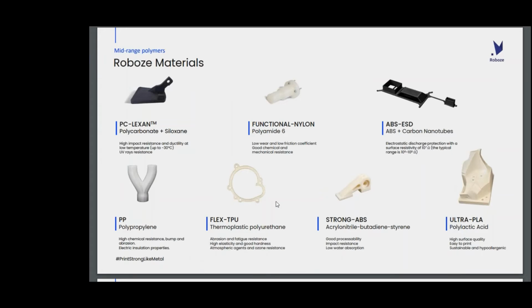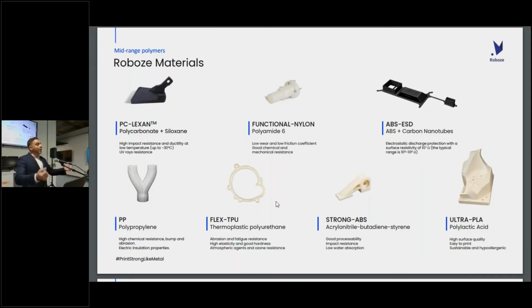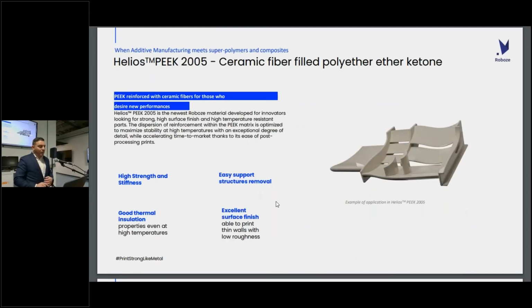So our angle on materials, now that we have built a system to process even the most temperamental materials at the highest grade: we print PEEK at around 35 to 40% crystallinity right off the machine. Now we can really go and look for functionalized formulations that can close the gap with traditional manufacturing in terms of performance, that can give a competitive edge to our customers and partners in terms of using different materials for specific applications, even on the engineering thermoplastic side. After all, if we're all using the same machines and the same materials, well, you already know where this is going, right? So let's talk about Helios PEEK.